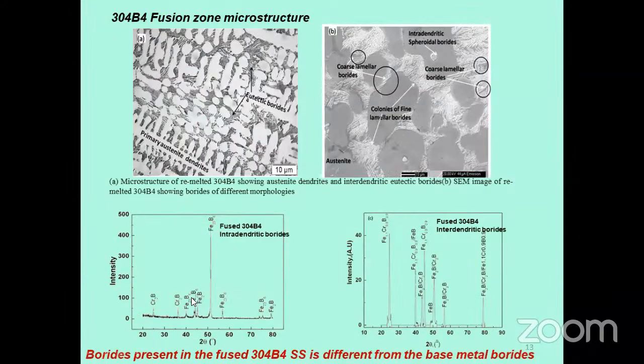Now coming to the fusion zone, when the material is being welded, it goes to the liquid state and resolidifies again. We have this type of microstructure: austenite dendrites and an interdendritic region with a fingerprint type of structure. They are all eutectic constituents. This is an SEM image of that, and we have a magnified view. Here we see these are all boride eutectics present in the interdendritic regions of the austenite dendrites, and we have different morphologies of these eutectic borides.